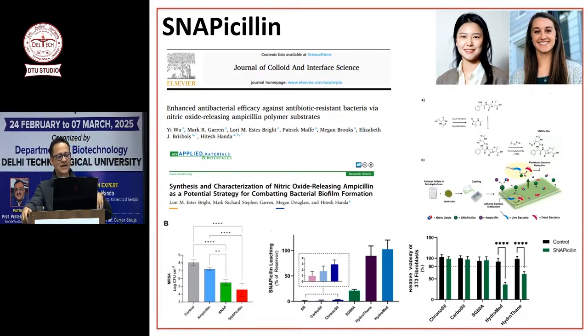Ampicillin is a common antibiotic and SNAP is a NO donor. So we covalently bound SNAP to the antibiotic, ampicillin and SNAP, and we call it snapicillin. Now the idea is, antibiotics cannot penetrate biofilms, right? You need 1,000 times the dose to penetrate. But NO can penetrate biofilms. So if you have a surface that's badly contaminated, you expose it to snapicillin solution. NO will penetrate the biofilm and can kill the bacteria, disperse the biofilm.